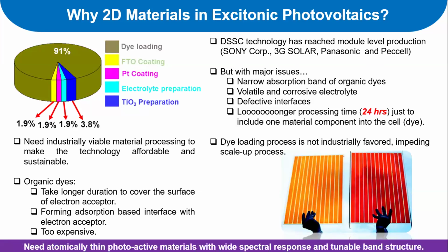technology to commercialize. The major disadvantage with this technology is that the major photo-absorption material candidates used have a narrow absorption band. It means they absorb very limited photons in a narrow absorption spectral range. They are not like silicon or gallium arsenide. And they are volatile, so we cannot use them in a very harsh environment, whereas silicon can be used. They also have defective interfaces, and the process time is a very major issue. They take too long.